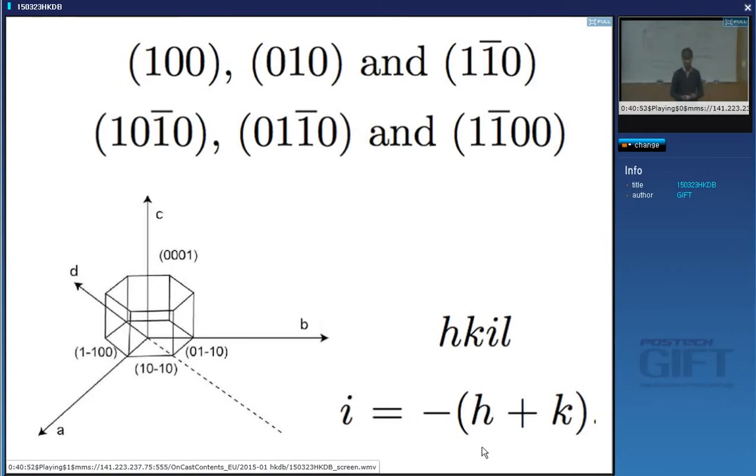Now, in the cubic system, that's very easy to understand, that if you have a direction which lies in the plane, then the plane normal is at 90 degrees, so the dot product is 0. Okay. But you can't do the dot product easily in non-cubic systems, so we will prove this later on very, very easily once we've done the reciprocal lattice. So we've got to design the 4 index notation for the hexagonal system in such a way that the Weiss zone rule still works for the hexagonal system.